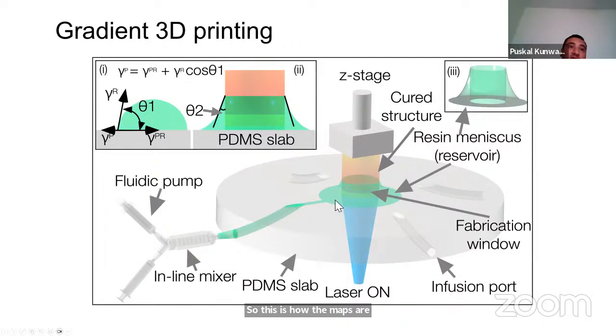Now, ideally, for printing a gradient structure where the resin composition changes each layer, you want the resin volume to be equal to the volume required to print a single layer. However, this is not the case. The volume is much higher, again defined by the contact angles θ1 and θ2.